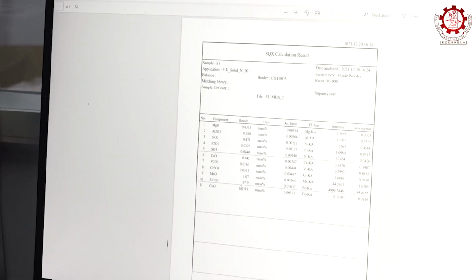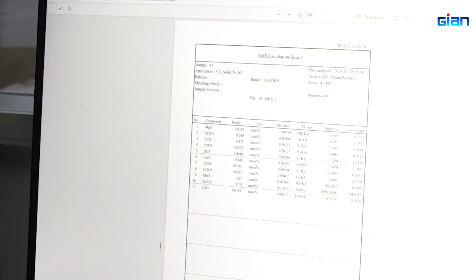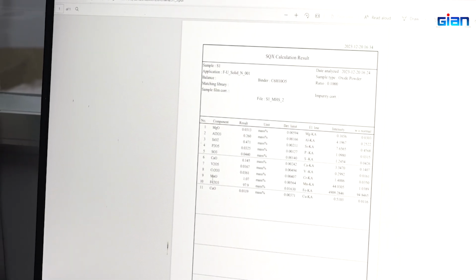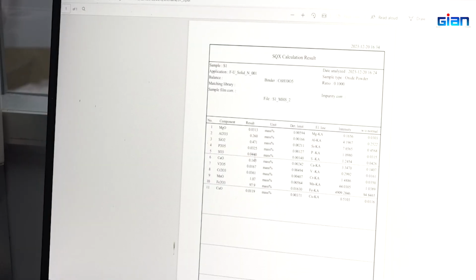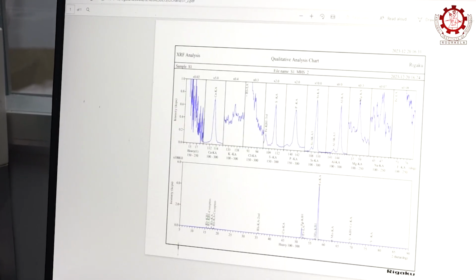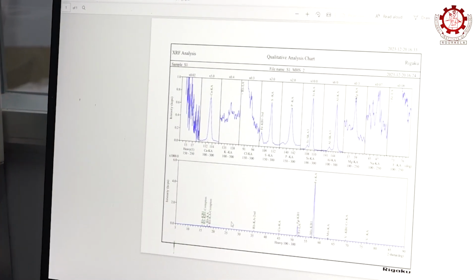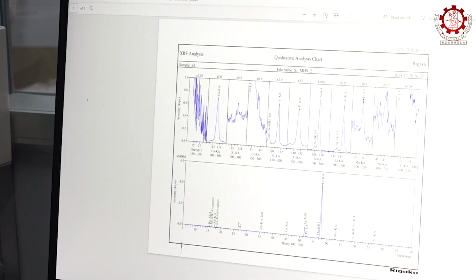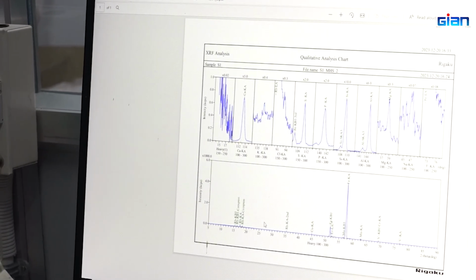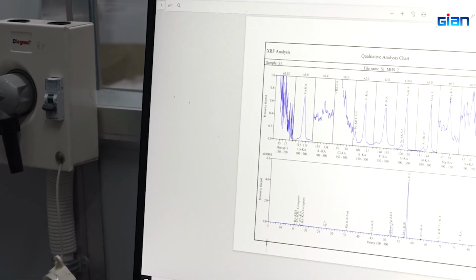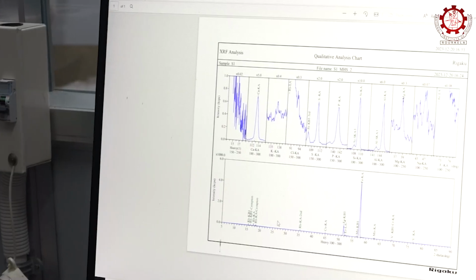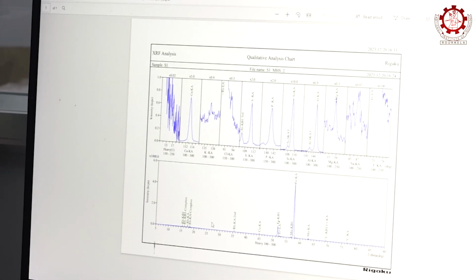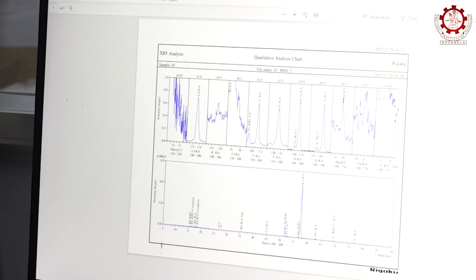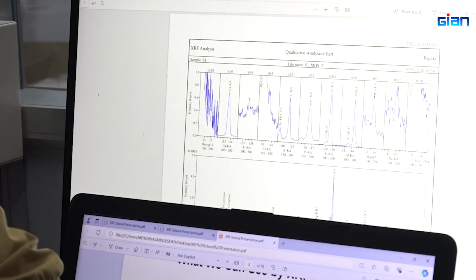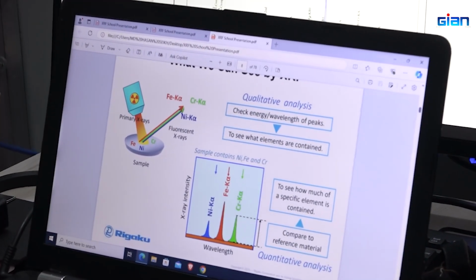Iron is present 97.9%, and then magnesium oxide, MnO, all other elements are point something. You can see the graph. The iron is 97%. According to the height of this wavelength compared to the intensity of this X-ray, the detector itself has a library. The height of the peak, this height, is compared to the reference material.